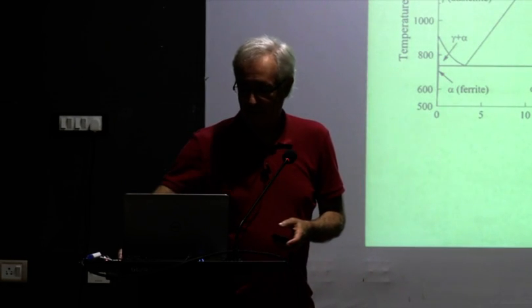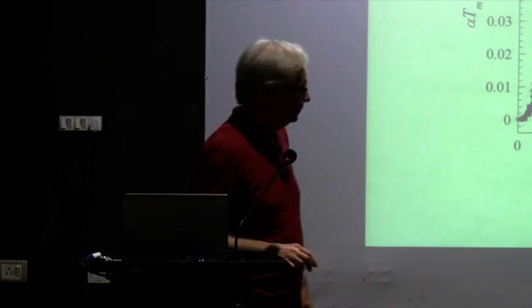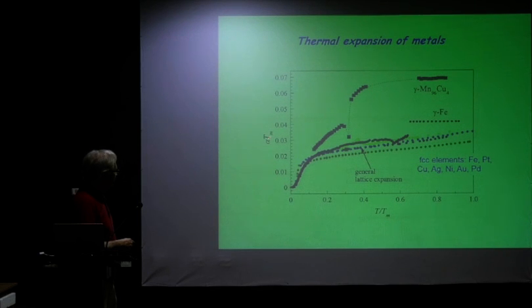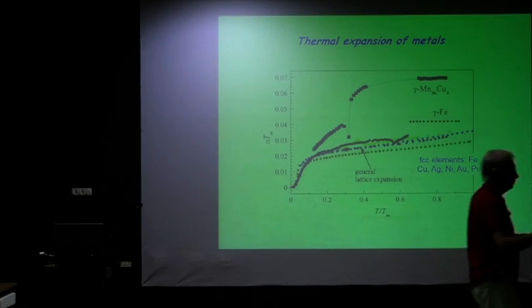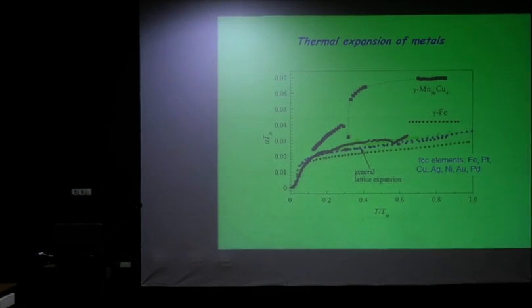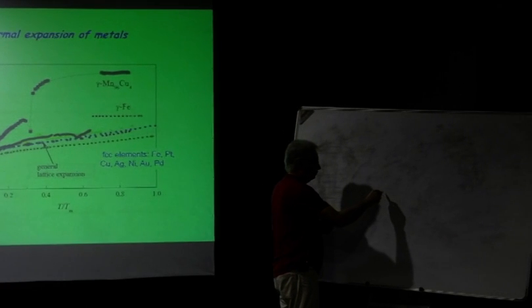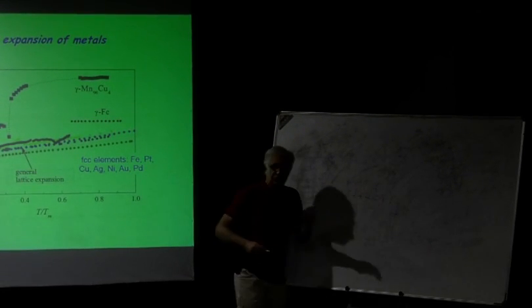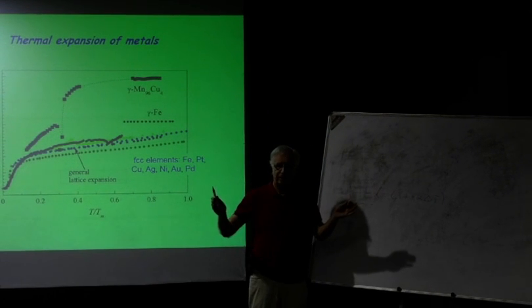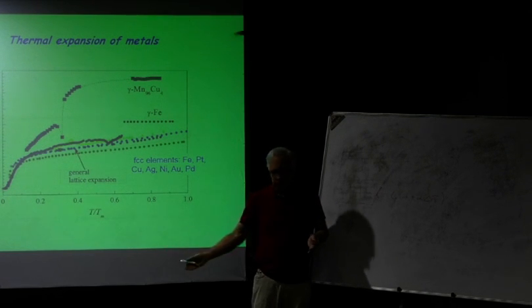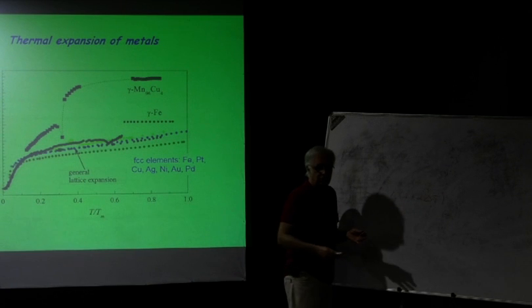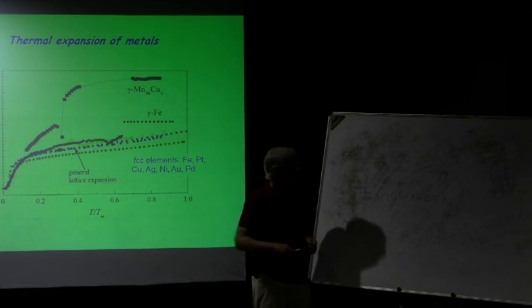Now, we come to a point where we want to look at the thermal expansion properties. So we have here a plot of thermal expansion multiplied by the melting temperature, that is, the temperature reduced to the melting point. The alpha Tm is therefore, when we write down that equation again, we have what? L equals L0 times (1 plus alpha delta T), yeah? And if we consider the length variation from the lowest temperatures to the melting point, then this delta T would be the melting point minus practically 0. So that would be Tm.